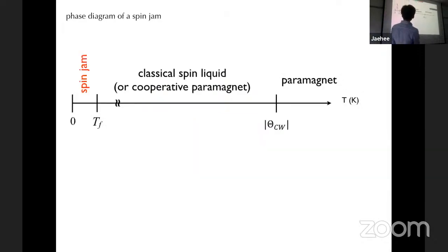So let me summarize this. This phase diagram for SCGO is the following, and I think it applies to all the spin jam states. There are two energy scales. One is the Curie-Weiss temperature, set by the J term. Another is a much smaller energy barrier produced by the quantum fluctuations. So when you cool the system down from high temperature, from the thermal paramagnet below the Curie-Weiss temperature, you'll be in what we call either a cooperative paramagnet or classical spin liquid. But then if you cool down enough, the system will freeze, and we call it spin jam. And the low energy excitations in this spin liquid state and in spin jam are different.